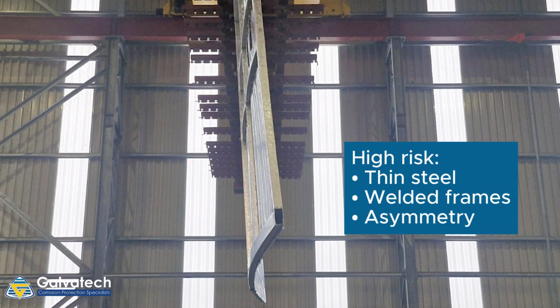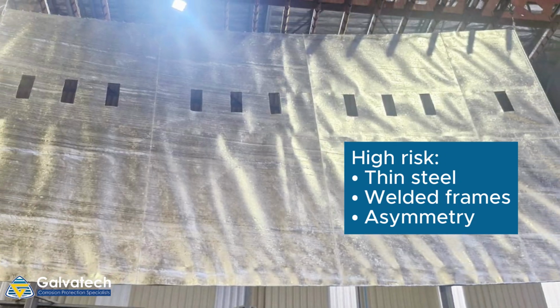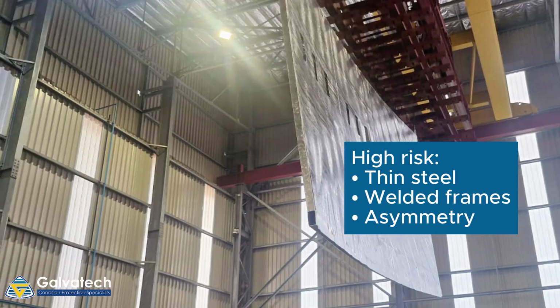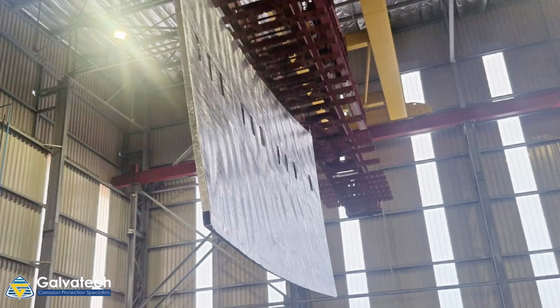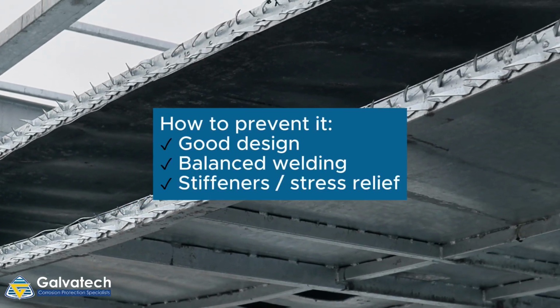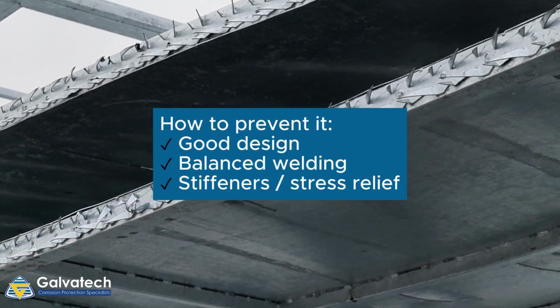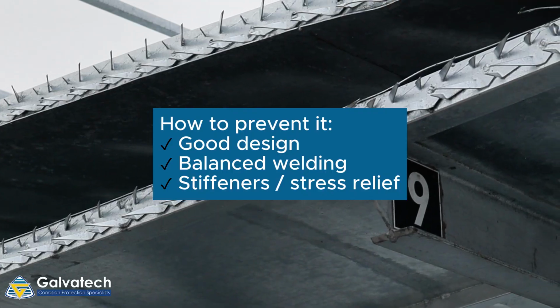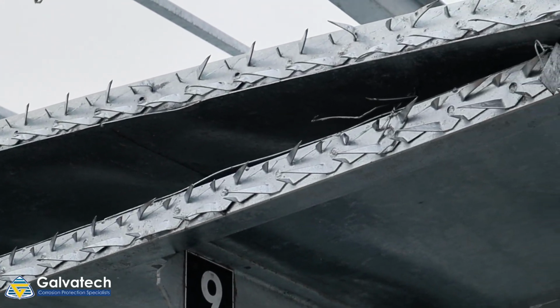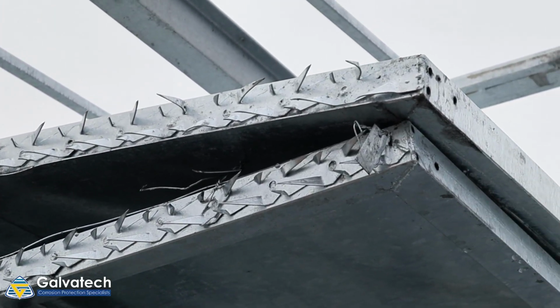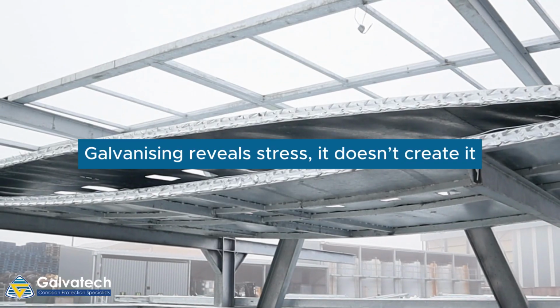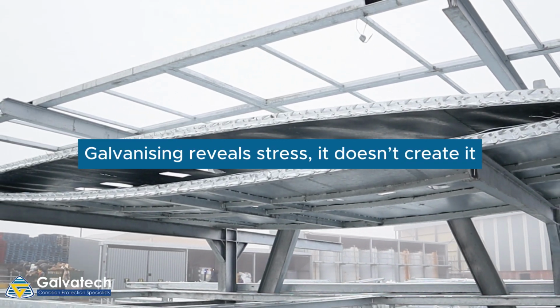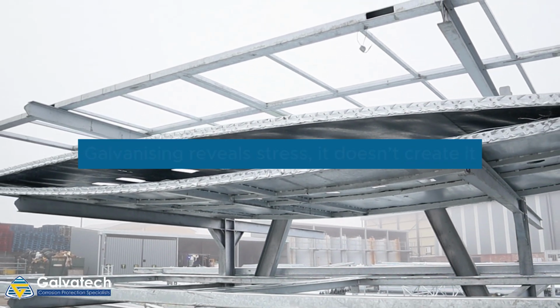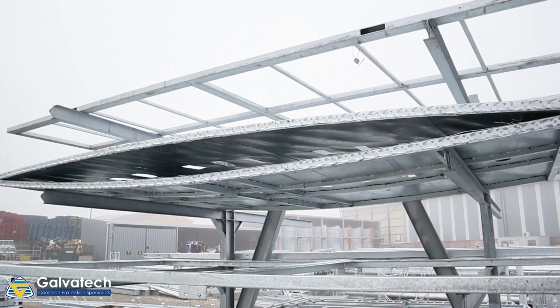Thin sections, asymmetrical designs, or heavily welded structures are most prone to movement during galvanizing. The key is good design and fabrication practice. Balanced welds, proper stiffening, and stress relief before the galvanizing all reduce movement. Hot-dip galvanizing does not create stress, it simply reveals stress that was already locked inside the steel.